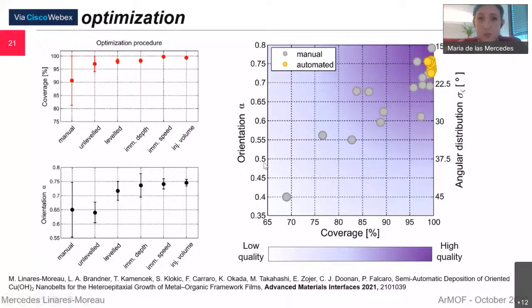It allowed us to move from this cloud of gray points, let's say that was the quality of the samples that we were obtaining with the manual procedure, towards this corner here, that is what we really want, the best coverage and the best orientation that we could have. We actually obtained 100% of the samples with the orientation above 0.7 and all of them also with the coverage above 95%.